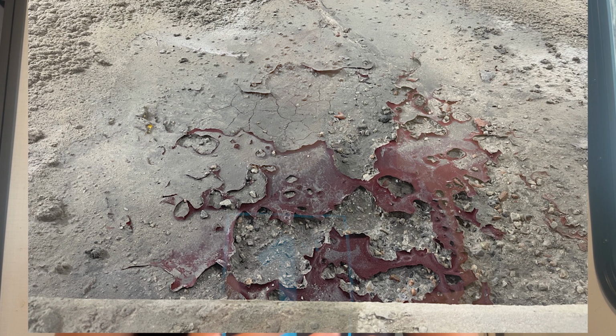First, let's take a look at the task at hand. And from this photo, you can see where the sulfuric acid has attacked the original lining system and the underlying concrete. For a surface like this, once the acid has breached that protective lining, it will more rapidly degrade the entire system. And you might be asking, why is that? And the reason is the chemical makeup of concrete and its natural porosity allows the acid to move through that concrete and attack it with relative ease.